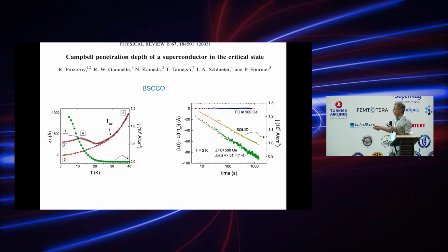Another remarkable feature of the data is that in the field-cooled state, not in the zero-field-cooled state, but the field-cooled state, there is no relaxation whatsoever. Nothing. There is no creep. I will stop here. I have slides which describe why we also do not expect to have creep in the field-cooled state, but since we are over time, let's stop here.